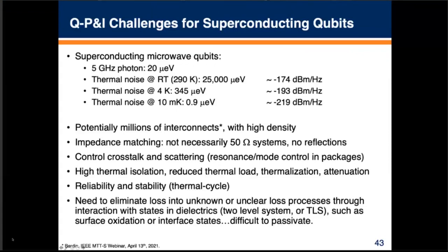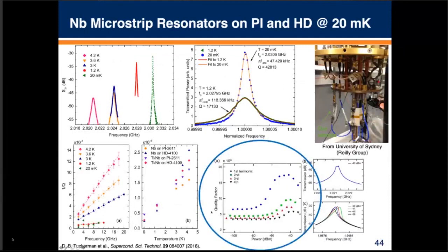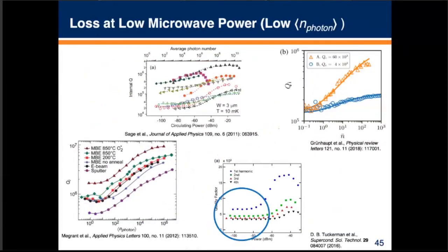Specifically, what I'm talking about there are these things that look like two-level systems, such as what you might find from surface oxidation or the interface states. And so it turns into a situation where it's really difficult to passivate these systems out. So we mentioned this earlier, of seeing that at low photon count or low microwave powers. And there's a handful of papers out there over the past several years with very similar situations. These are done at very low temperatures with very clean and much higher Q structures, but you're still seeing this in some of the similar packaging materials at these temperatures as well. So for these low photon count systems, your two-level systems are not saturated, and so they can absorb that when you have a low number of photons.